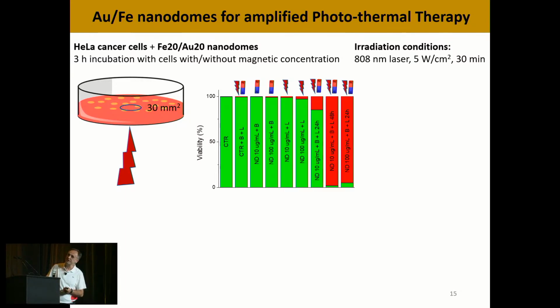And now when we concentrate the particles with a magnet, with the laser on, with 10 micrograms, after 24 hours there is a considerable decrease. If we wait for another 24 hours in these conditions, we see a large decrease in cell viability. But when we try the same with 100 micrograms per milliliter, we see that already at 24 hours there is a large decrease in the viability.